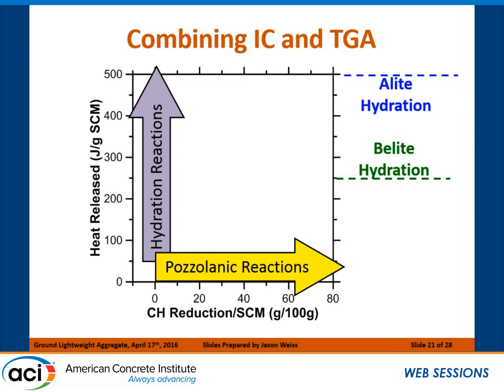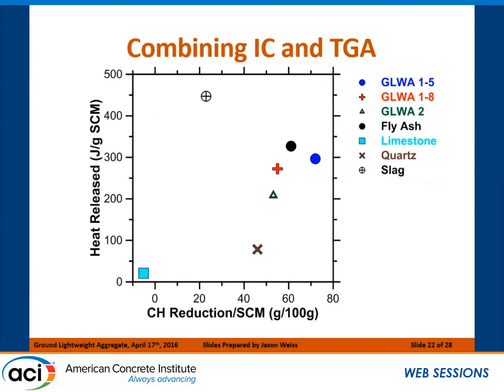So essentially, if we plot it with heat released at a particular age versus the amount of calcium hydroxide reduction, as we go further up this graph, we see more typical hydration reactions. All right, we see more heat being liberated. Alite's going to be somewhere up here in this 450 to 500 range. Belite's going to be somewhere in this range over here. And as we move toward the right-hand side, for the audience, we're going to see more pozzolanic reaction taking place in the system.